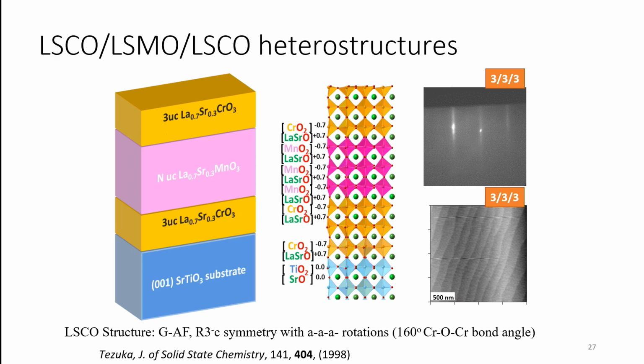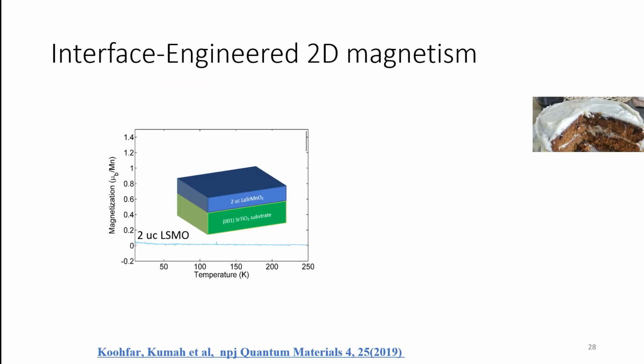So if we ended up finding that these materials were magnetic, we knew that it was coming from the LSMO and not the LSCO spacer layers at that interface. So here we're going to try and change the electrostatic boundary conditions and see if it leads to recovering magnetism in the system. Right, so going back, a 2-unit cell thick film is effectively dead.